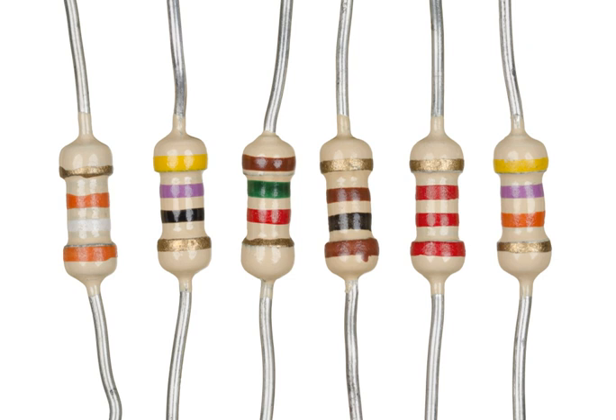Low-power thin-film resistors can be damaged by long-term high-voltage stress, even below maximum specified voltage and below maximum power rating. This is often the case for the startup resistors feeding the SMPS integrated circuit. When overheated, carbon film resistors may decrease or increase in resistance. Carbon film and composition resistors can fail open circuit if running close to their maximum dissipation. This is also possible but less likely with metal film and wire-wound resistors.